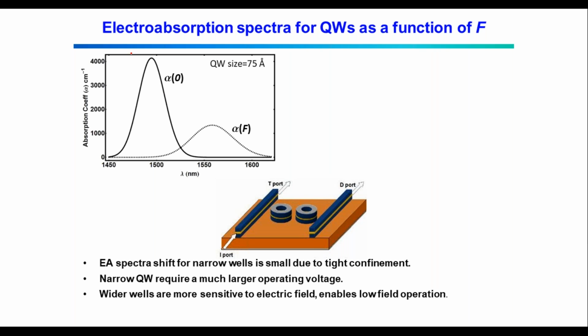So in fact, you can actually calculate all this. You can calculate the absorption spectrum for an optical switch. Basically, you have the resonance signal at this point. If no fields are applied to the rings, your resonance signal would appear at this point. Now once I apply the electric field to the rings, there's an absorption happening inside the ring, because of which you would also have a change in the refractive index of the ring. So this change in absorption would cause a simultaneous change in the refractive index of the ring, and accordingly the resonance signal would now appear at the T port. So the light will not appear here, the light would now appear at this point.